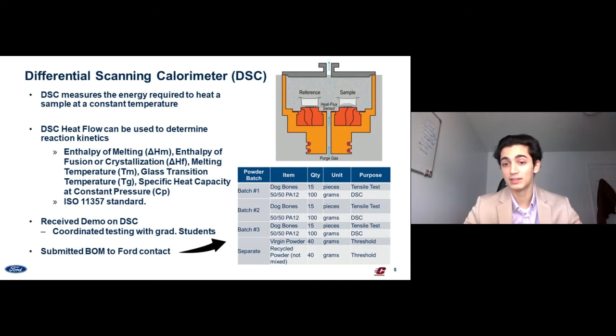So what we did was submit this bill of materials that you can see on the right side on the bottom. You can see that we had 3 different batches where we had 100 grams of powder for each batch. And we had 50/50 for 2 or 3 batches. And then we had another 4th batch where we were testing recycled powder. And then we were also testing completely virgin powder. So we have completely virgin and completely recycled powder, which would set the threshold for us. While the 50/50 powder, that's to see if the 50/50 powder is good quality or not.